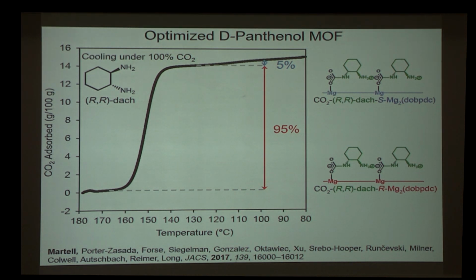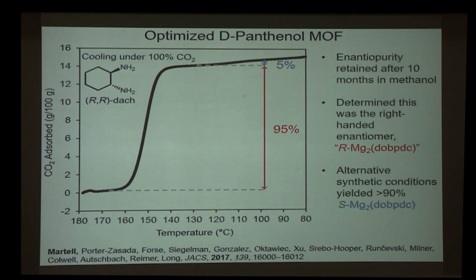I found that by increasing the amount of panthenol in the reaction and tweaking the reagent concentrations, I could succeed in creating a MOF preparation that was 95% enantiopure. And importantly, I found that storing this material in methanol for 10 months did not impact the enantiopurity, which is important because it indicates good stability in this protic solvent. In data I don't have time to show you, we found that this MOF was the right-handed enantiomer, which means the structure that contains right-handed helices. And separate alternative synthetic conditions yielded the opposite enantiomer with greater than 90% enantiopurity.